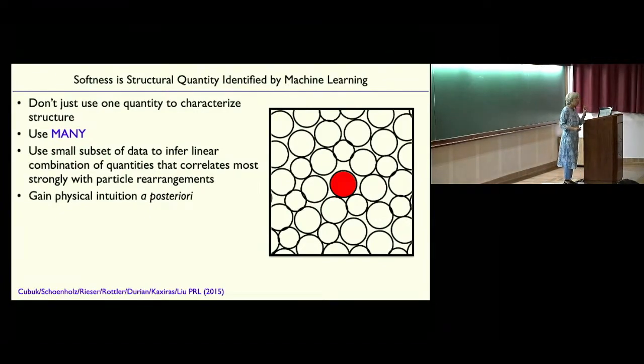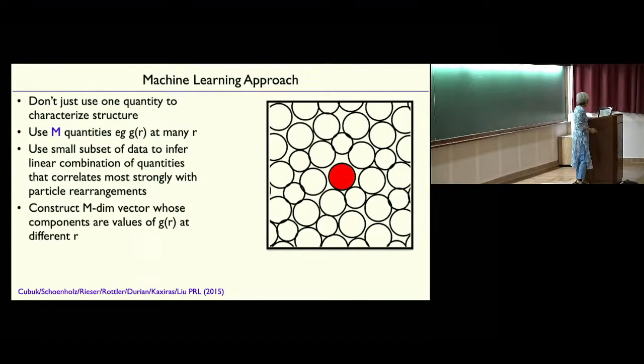And then you use a small subset of your data where you say, okay, I know that these particles are just about to undergo a rearrangement, whereas these other particles haven't had a rearrangement for a very long time, and you use that to train this thing. How do you do that? So we have, let's say, m quantities, which are the local pair correlation function at different radii. Now we put this into a high dimensional space. On one axis, we have g of r at one value of r. The orthogonal axis is g of r at a different value of r, and then a third value of r. If you have m different values of r, then I have an m-dimensional space, and where I am in this m-dimensional space tells me about my local structural environment.